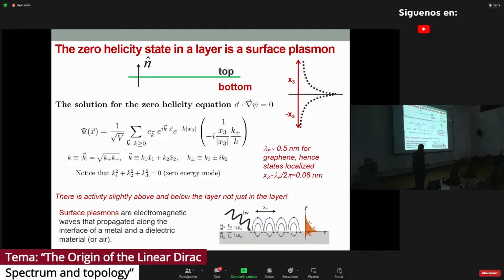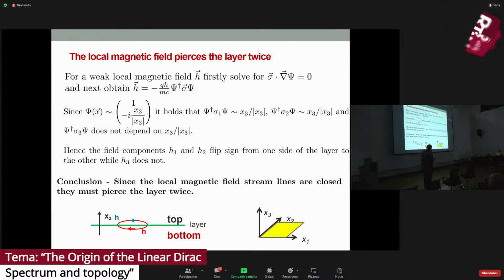We know surface plasmons are electromagnetic waves that travel on surfaces. Notice that the localization, if you take the largest momentum, Kf, say 0.5 nanometers for graphene, is about 0.08 nanometers. So it's atomic scale localization around the layer. That's what the theory is saying. But now you compute the local magnetic field. There is a local magnetic field associated to it. I'm not taking an applied field here, for simplicity.